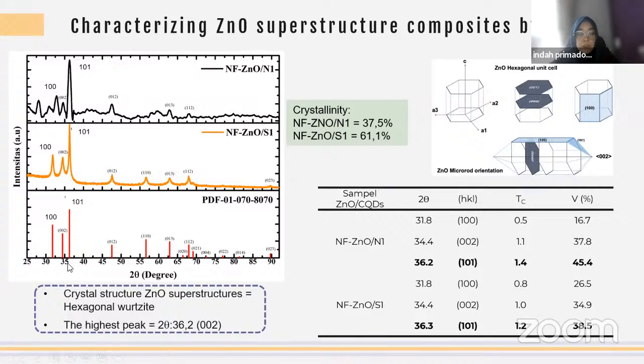superstructure. And here you can see the highest peak is not 002 like what we observe in the one-dimensional nanostructure, but we observe 101 as the highest peak. So the preferred orientation of this prepared material is in the 101 direction here.